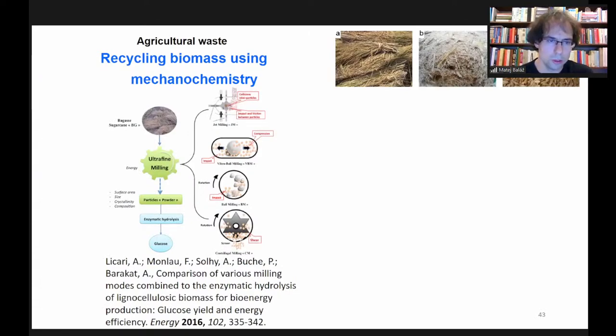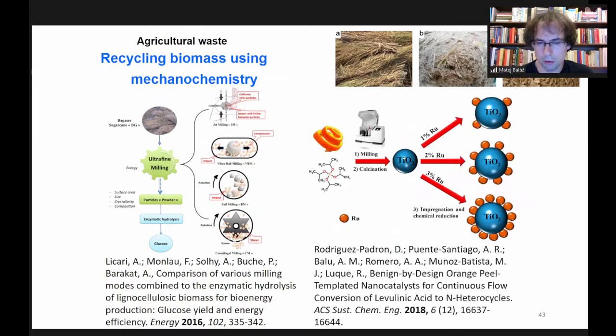And now two examples. Sugarcane bagasse was treated by high energy ball milling by using three different mills: a vibration one, a traditional ball mill, and a centrifugal mill. And in this study, the authors examined how the result of enzymatic hydrolysis depends on the mill used. And another, my favorite study, shows that orange peels can be used as efficient capping agents for nanoparticles of titanium dioxide doped with ruthenium also. And they can then be used as very efficient catalysts of organic reactions. So again, biomass by the treatment of mechanochemistry can be transformed into useful material.